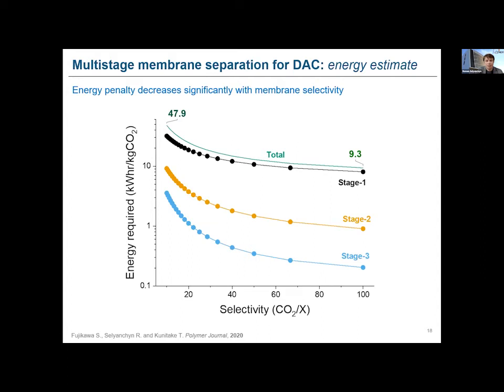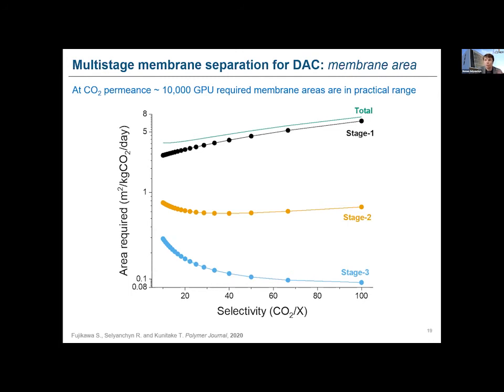Also, we have estimated the energy required for the CO2 capture, or CO2 preconcentration, if you will. And what we can see is that depending on the selectivity, we can change this energy in a very broad range. So this green line indicates the total energy of the capture. As you can see, it's very close to stage 1. It means stage 1, which works with the highest amount of gas, is of course the most energy consuming. And the total energy can be as low as 10 kilowatt-hours per kilogram of CO2 captured in this setting. And also, because it is very important to estimate how big the membrane should be for the separation, here we can see the dependence of the required area for kilogram capture per day, depending on the selectivity.